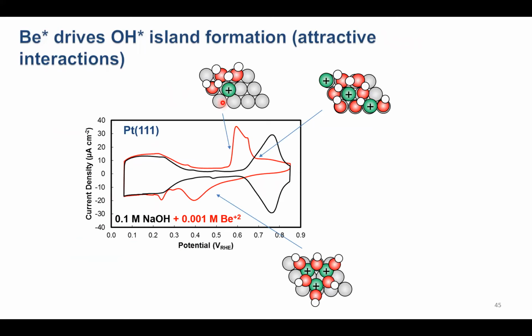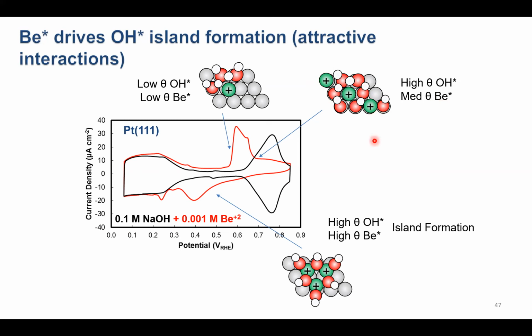So I showed briefly some DFT results. I'll show more in a few slides, showing that if we have a low coverage of beryllium that promotes a low coverage of hydroxide adsorption, relative to no cation or relative to a sodium cation. Once we finish this add layer, though, it becomes favorable to adsorb a higher coverage of beryllium into the add layer because we have mutually attractive interactions between the adsorbed beryllium and the adsorbed hydroxide. Further, if we scan slowly enough, what happens is this add layer of high coverage OH and high coverage beryllium actually reorganizes and forms islands on the surface where locally we have a very high coverage of beryllium and high coverage of hydroxide that is very stable because of these mutually attractive interactions between the adsorbed beryllium and adsorbed hydroxide.